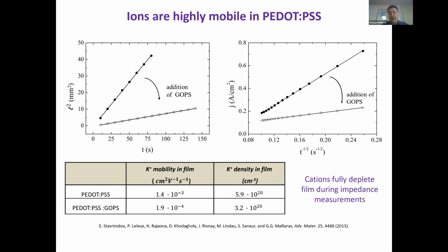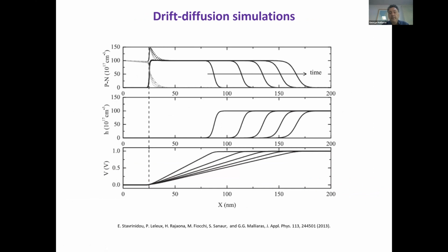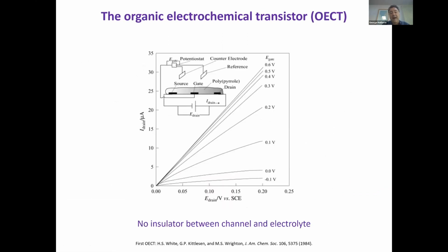And you end up with values that show that, first of all, cations fully deplete the film during impedance measurements, both because their density is such that they can compensate every anion in the film, but more importantly, they have enough mobility. They can move fast in and out of the material. So when you do your impedance measurements, they can completely deplete and repopulate the sample during a scan of the frequency up to fairly high frequencies. You can model this with drift diffusion simulations, so you get beautiful profiles, the same features that you see in the experiments you can get by a drift diffusion model. So again, fully capacitive type of behavior.